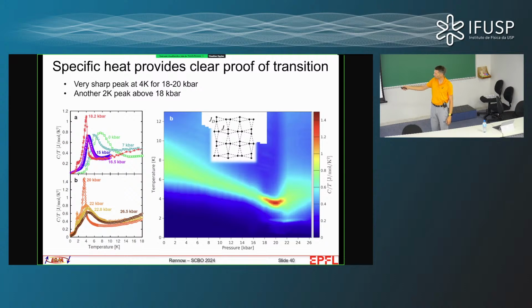It's this broad bump, which essentially represents the thermal activation up to the triplet excitation. Okay, fine, nothing interesting there. But then once we applied pressure, once Julio applied pressure, this peak moves down to lower energy. That's fine. The gap is coming down in temperature, so it's natural that the peak also moves down. But it becomes sharper. It becomes super sharp down here. And then actually a new peak develops down here.